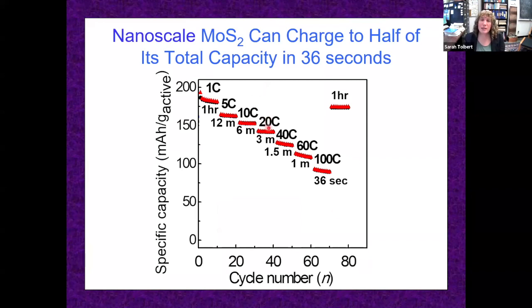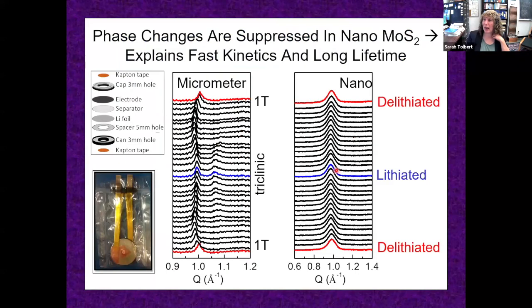Before, I went up to 20 C, a 3-minute charge. Now we're going up to 100 C, or a 36-second charge, and the material has half its capacity in a 36-second charge. That's really fast. This material has a phase transition, and in the bulk, you can see that that phase transition is indicated by the appearance of this extra peak when we put lithium in it.